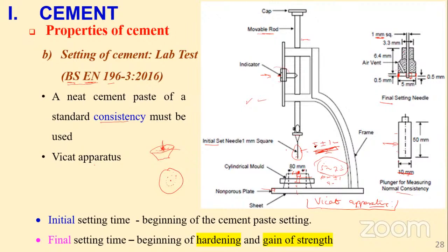So for initial setting time, we prepare a cement paste, and then you see what it takes to penetrate at that point. If you release the needle and it goes beyond this, of course you had prepared your cement paste to be standard, so it should not go less than this. If it goes beyond 5 plus or minus 1 millimeter, then you know your cement has not started setting. So if it's between 4 and 6 millimeters, then you know the initial set has occurred.